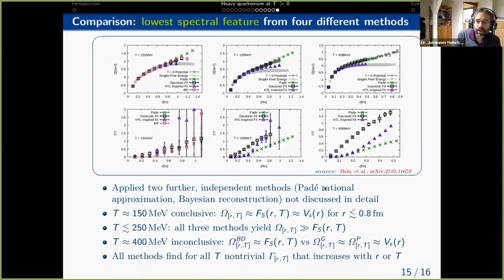One is called the Pade rational approximation, where we first Fourier transform the lattice data to imaginary frequency space, then interpolate, then analytically continue to real frequency space, and then directly obtain results for the position of the lowest feature and for its width. The other is the Bayesian reconstruction, which I can't go into in detail here in the brief discussion. And what we now see is that at low temperatures, at the crossover, all of these results that we get are essentially consistent.